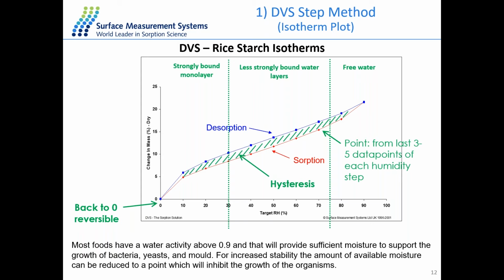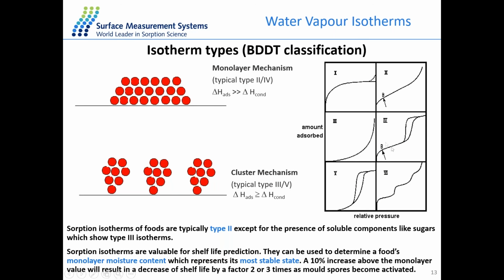And if we also use some organic vapors and do the isotherm for some organic vapor like hexane, octane, or ethanol, we can get a type 2 or type 4 isotherm. We can also use the isotherm to calculate the BET surface area of the material. So for example, here we have different types of the isotherm. The type 1 isotherm is typical for some microporous material. And the type 2 and type 4 isotherm is for the monolayer formation of the probe molecule on the surface, and then multiple layers on top of the monolayer.